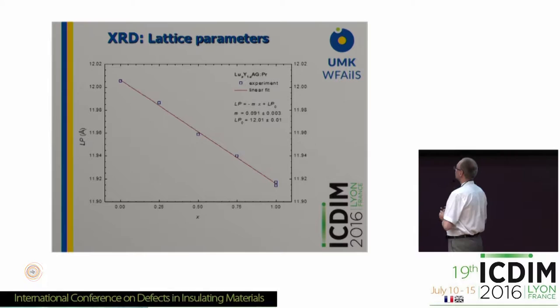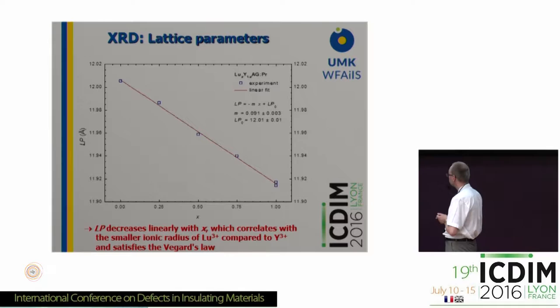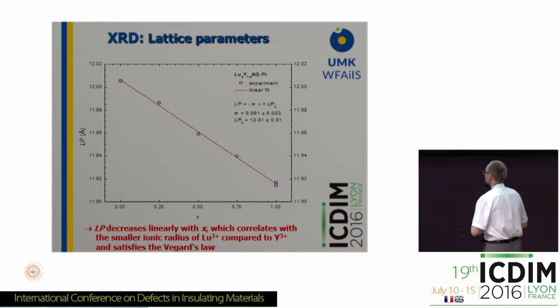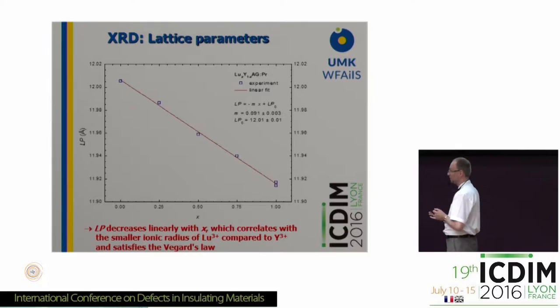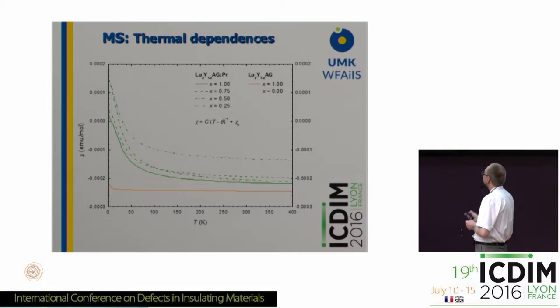These are the lattice parameter values derived from XRD studies — X-ray diffraction studies. If we denote the lutetium-to-yttrium ratio as X, then when we increase the amount of lutetium and decrease the amount of yttrium, the lattice parameter goes down. This is closely related to the fact that the ionic radius of Lu³⁺ is lower than that of Y³⁺, giving a nice linear relation which satisfies Vegard's law. So this is another sign that everything is correct with these crystals.